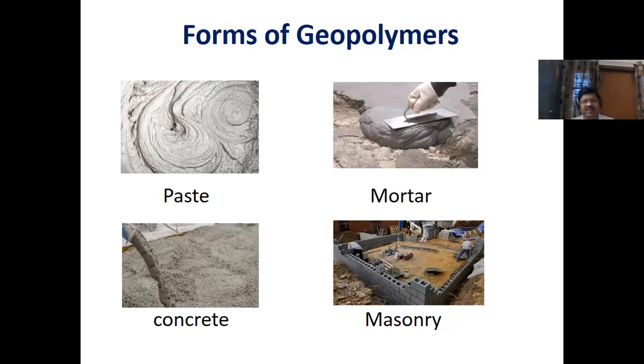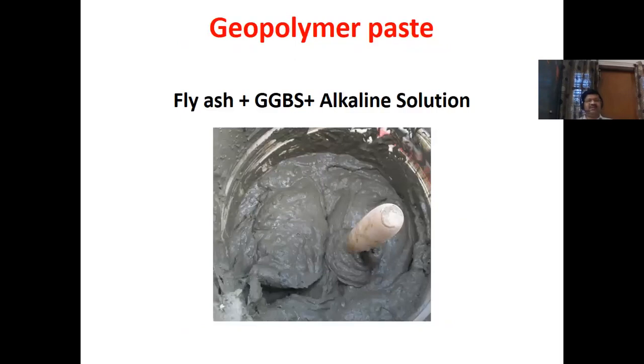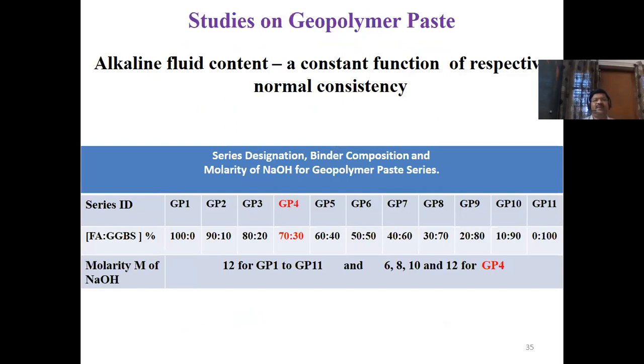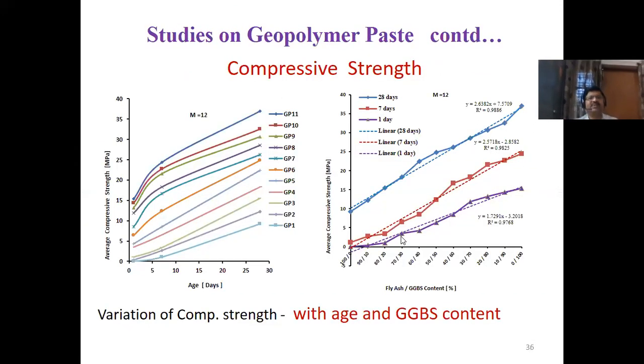What is the paste? We add binder, there is fly ash and GGBS and alkaline solution. That's all. Now the result comes. See here. We have used 11 samples, GP1, GP2, etc. till GP11, wherein the fly ash GGBS combination is varied from 100, 0, 90, 10, etc. till 0 to 100. That means in the first case, fly ash is 100%, GGBS is 0. Second one, fly ash is 90. I'm slowly increasing the GGBS when compared to fly ash, right? And this is only the experiment program, and this is the result.